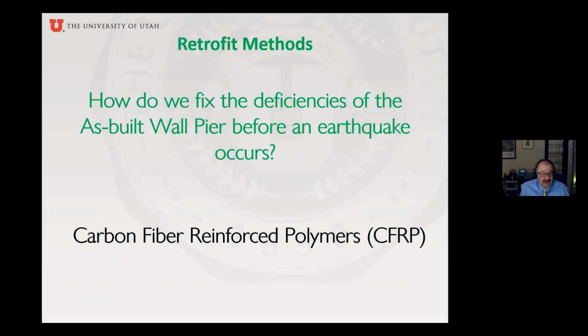Now, a little side story here. I started working with carbon fiber reinforced polymers in the 90s. The Utah Department of Transportation found that a lot of the bridges on Interstate 80 actually had corrosion, and they wanted to postpone replacement of these bridges, and they were trying to buy time. Well, how do you buy time? So we used carbon fiber composites to wrap the columns and the joints and the beams so that they could buy time and replace those bridges in a more regular way, rather than trying to replace 15 bridges at once. So that's how I got introduced into carbon fiber reinforced polymers about 30 years ago.